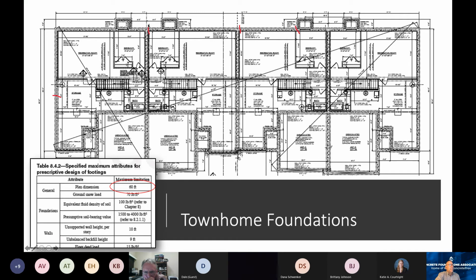And they were getting cracks at these intersecting walls where I've got the red lines, crack here, and then the crack I just showed you is right here. They were also getting that crack I showed you earlier over here on this sidewall. The crack development at these intersecting walls is all associated with the fact that you've got such a long wall across here. They had less than half of the amount of steel that you could calculate that they required. And so the shrinkage was forcing cracks where the points of restraint were, which are these intersecting walls.